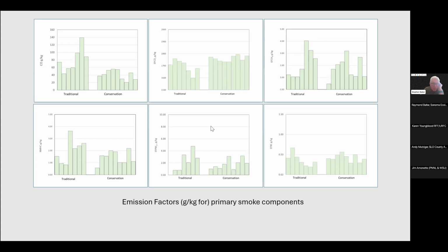And for non-methane hydrocarbons, it was kind of the same thing as you saw for methane. We had one fire there, you can see, that had a lot higher value for traditional than the rest of them. And generally the conservation non-methane emission factors were lower, although kind of a mixed bag.